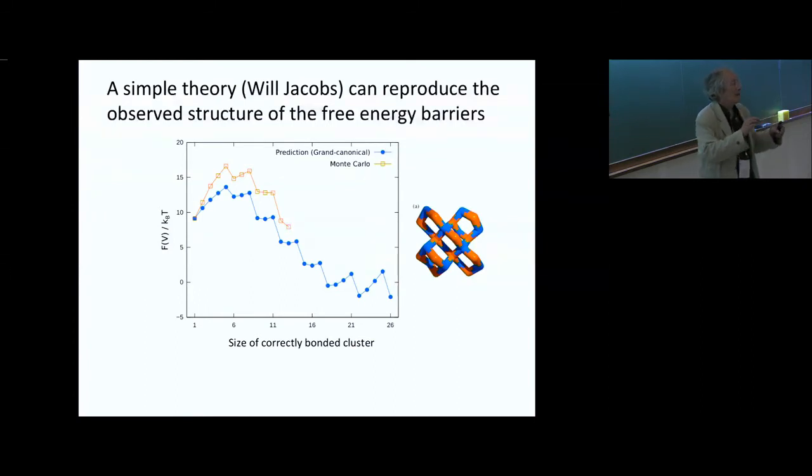So why is it zigzag? Well, the reason is that you have a diamond lattice. And so if you have a diamond lattice, you first have to bind two particles together. But actually, that is not stable, so that a dimer tends to fall apart. Then you get a trimer, actually still not stable. You gain some binding energy, but again, it is exactly the same as what you gained in the previous bond, and it easily falls apart.